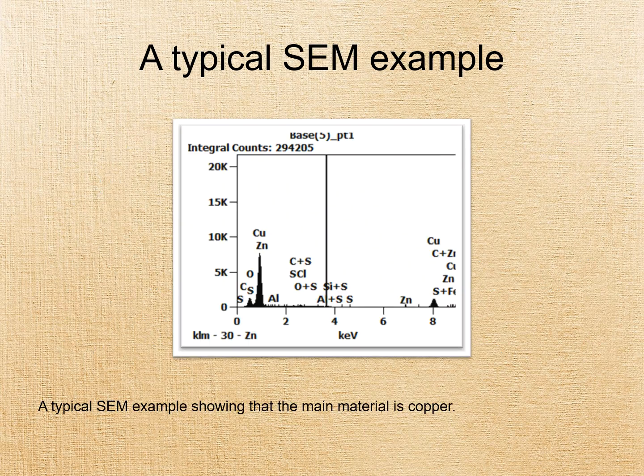You can see the copper and zinc in this plot from the scanning electron microscope. You can also see carbon, silica, zinc, aluminum, and oxygen. The aluminum is probably a contaminant or a false reading from the microscope. The silica and carbon are probably from sand on the surface of the aiglet.